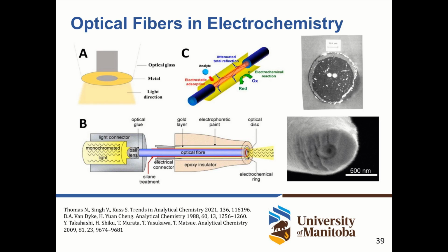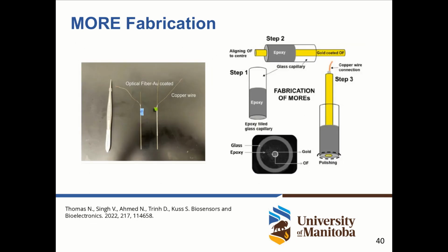In literature, you can find various very interesting approaches where the glass is either a ring around a metal, shown in A, or we have a side illumination or detection of light-sensitive events at electrodes. But as you can also appreciate on the right-hand side, the geometry of these probes in the past has not been very consistent. Especially when we image very complex systems like cells, the reproducibility and repeatability of experiments is incredibly important because we need to gather a large amount of analytical data sets. So we were aiming first to develop a method for the development of these micro-optical ring electrodes for SECM applications